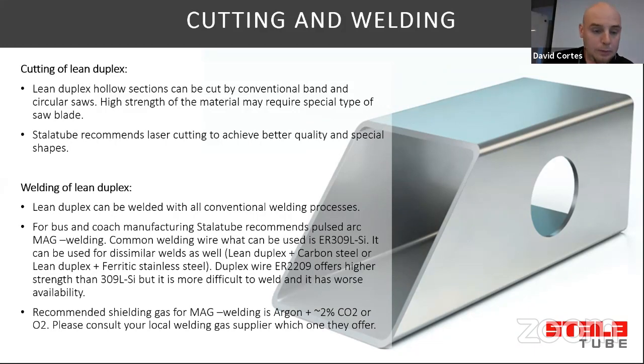Then Lean Duplex can be welded with all conventional welding processes. For bus and coach manufacturing, Stalatube recommends pulsed arc MAG welding. Common welding wire that can be used is called ER309LSi. So it is an austenitic wire. So it can be used also for dissimilar welds. So if we have to weld together Lean Duplex and carbon steel or Lean Duplex and ferritic stainless steel. Duplex wire ER2209 is also available.